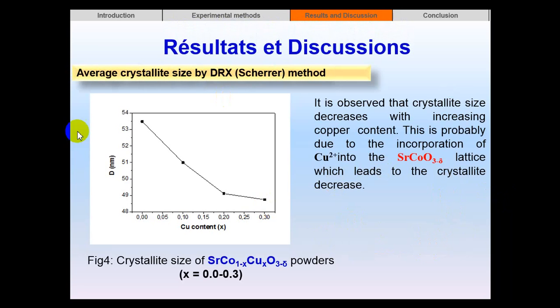It's observed in figure 4 that the crystallite size decreases with increasing copper content. This is probably due to the incorporation of Cu2+ into the SrCoO3-δ lattice, which leads to the crystallite size decrease.